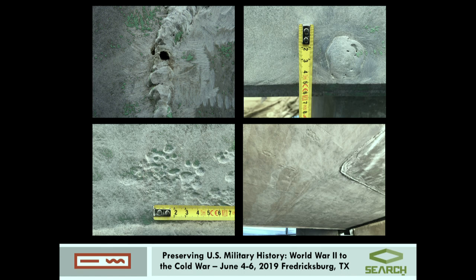Bottom left, you have original corrosion, and you can tell that because you still have paint over there, you see? So you can tell that this corrosion was pre-existing. And on the right, you have runoffs, and you've got an area that was repaired, and you see almost as if it had been repaired yesterday, the tool marks.